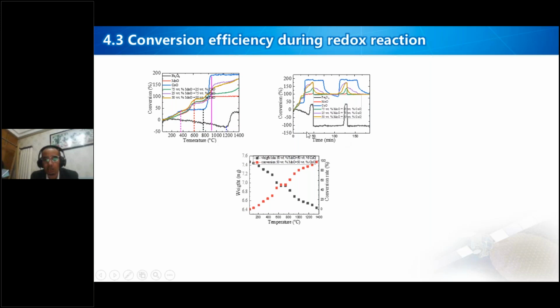The conversion also has to be computed over the whole of cycle 1 and cycle 2. We always see sinusoidal behavior for the different compositions. Still, among these, the 50% by weight manganese and cobalt oxide has a good conversion rate compared to the others. It is in a stable condition. The conversion in both cycles is unstable for the others. So we select this 50% and then compare the graph of weight loss and conversion at the same time within one graph. It is a kind of mirror image, it seems.